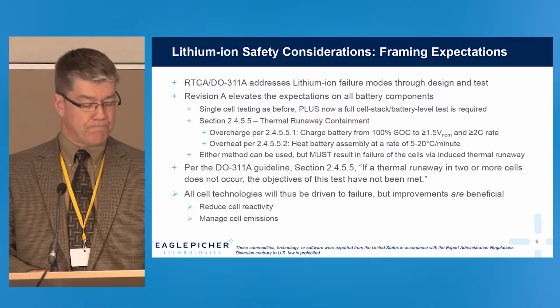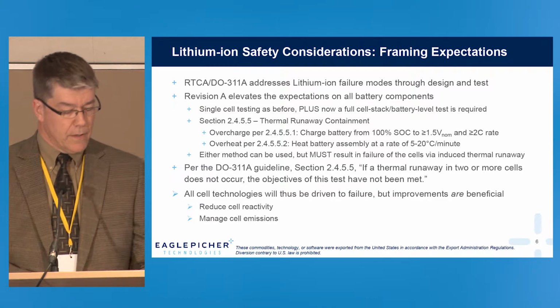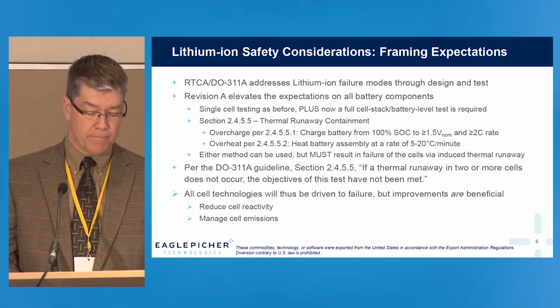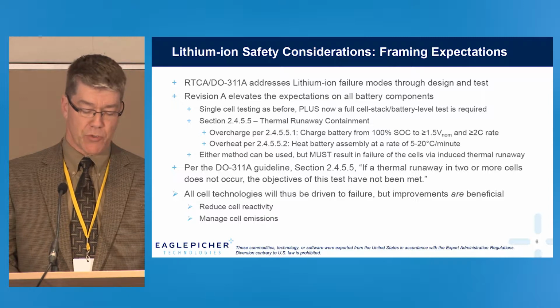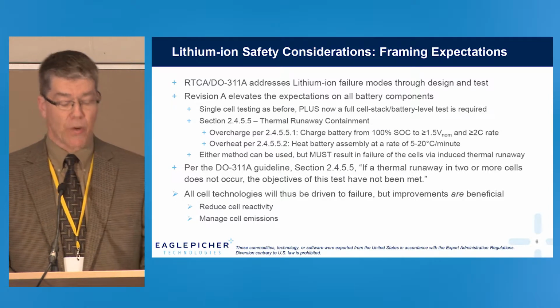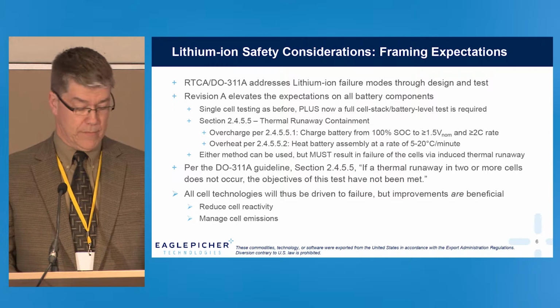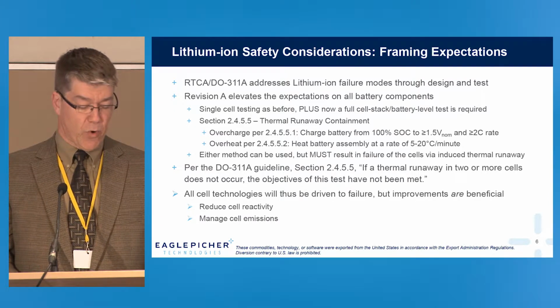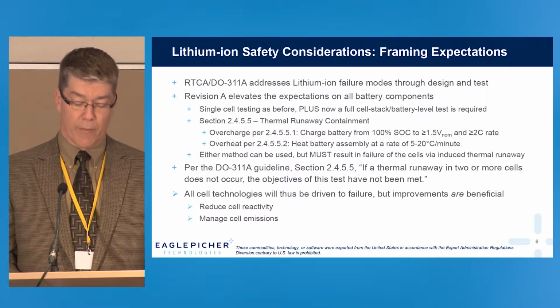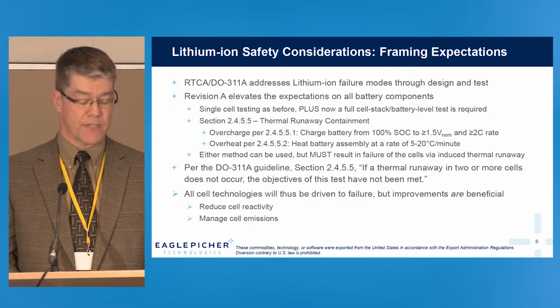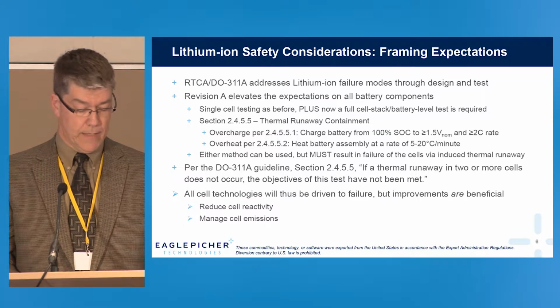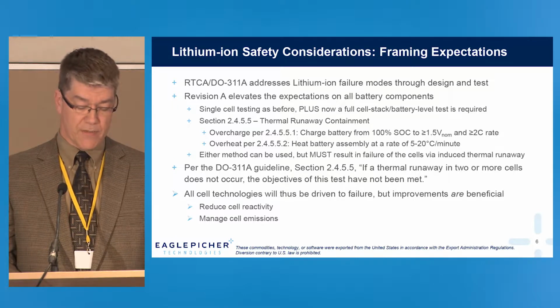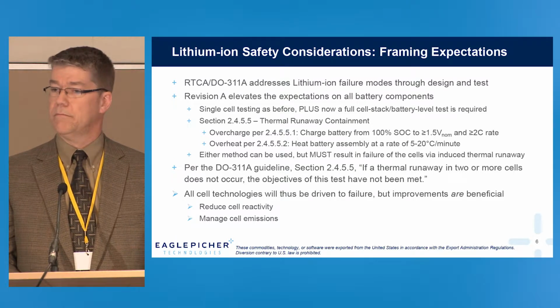So what do we do? The RTCA formed a special committee some time ago to review lithium-ion issues and the inadequacy of the then-current DO-311 standards. Two far more rigorous expectations for testing were implemented at the battery level. One was overcharge, fundamentally an expansion of the prior single-cell test, or overheating, a new test introduced to force the cell decomposition and to drive the cell into an ultimate failure.